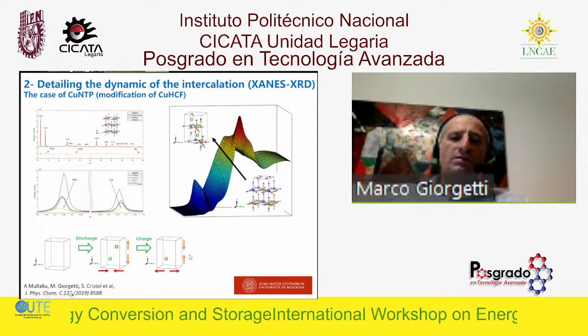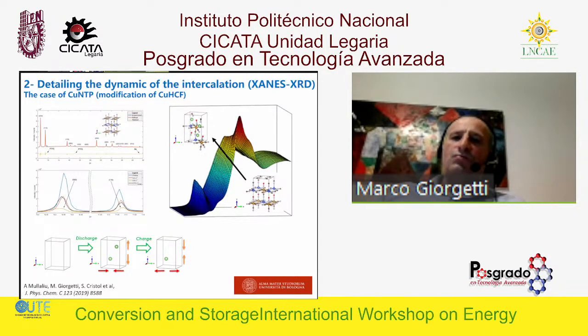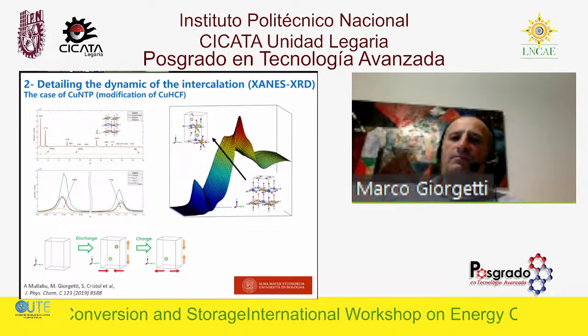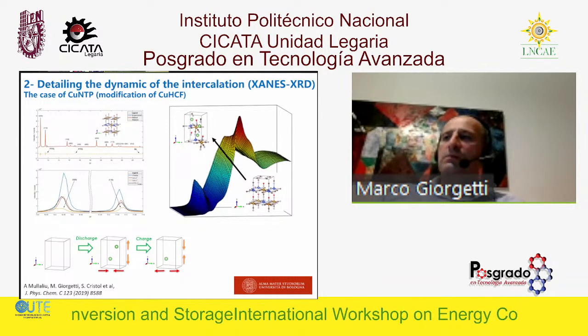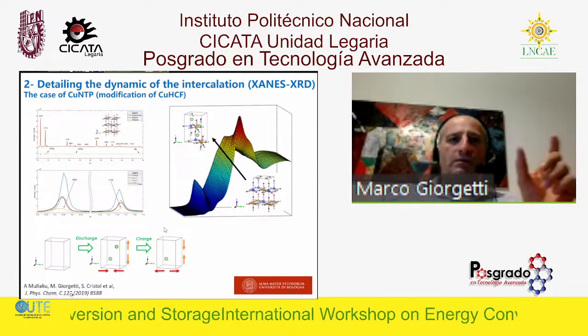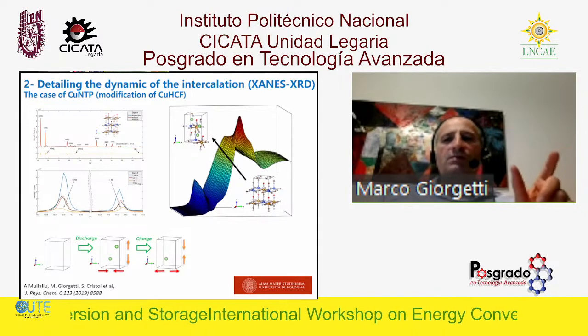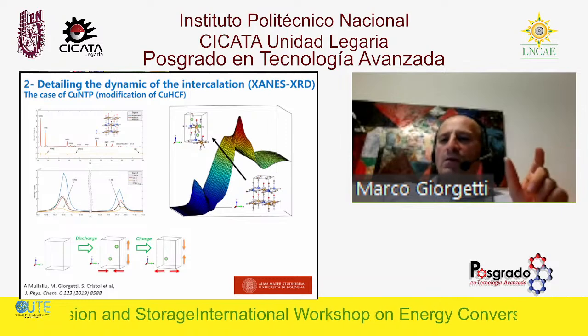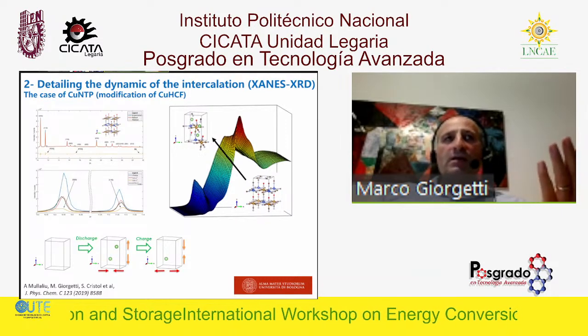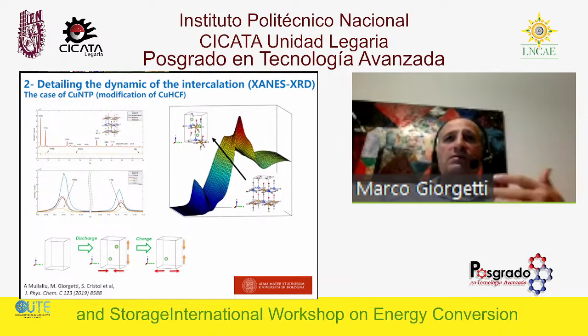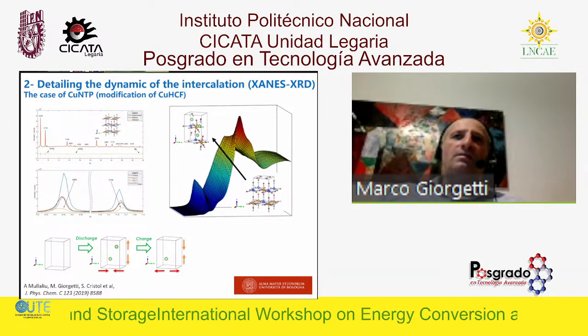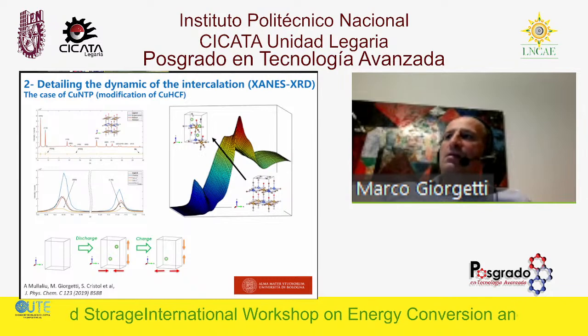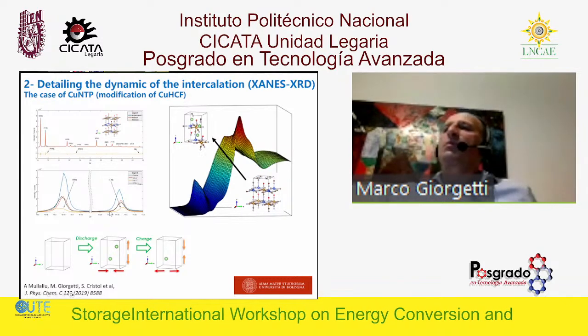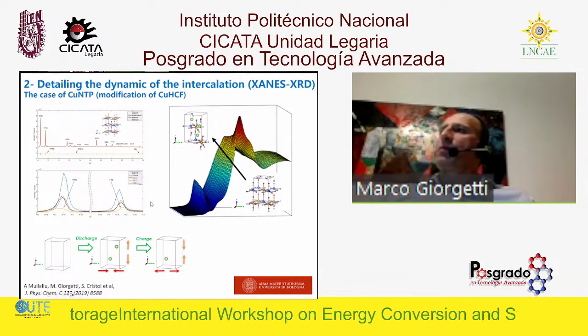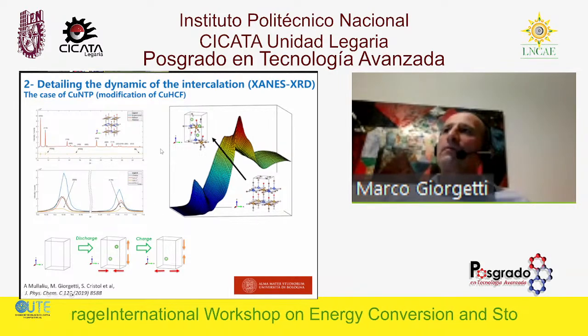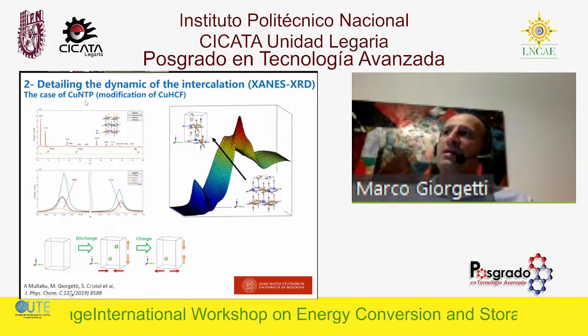Here the motivation was to try to put another, let's say, electroactive portion on the structure, because, okay, even this very interesting structure, the metal hexacyanoferrates, we know that anyway, the volumetric energy density is kind of low because there is a lot of void inside, okay? This zeolitic channel that we have inside. So it's possible to make something active. So we ended up with the copper nitroprusside material.